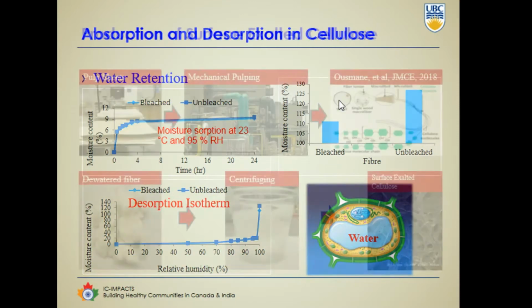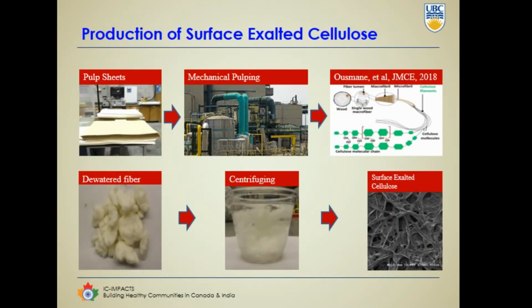But we went one step further. We said, oh, wait a second, we can fibrillate cellulose even more. So we start off with recycled cellulose, which is essentially a byproduct of the pulp or paper industry. We send it to a mechanical pulping unit where we can fibrillate this cellulose even further. When I get this fibrillated cellulose, I centrifuge it, and I get a material which has even greater water absorption capacity because of the fibrillation. I have a much greater surface area, and now I get a much better response to water absorption, and it will continue to desorb, giving out that water when I need it, which is a wonderful way to do it.